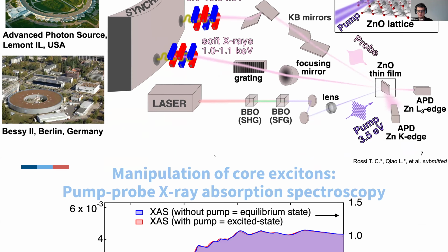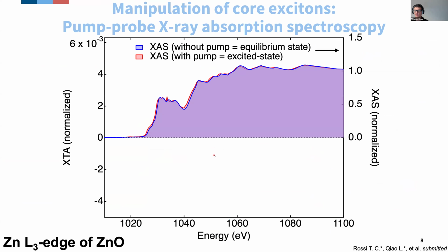And so with this, I will finish my introduction by just showing how experimental data are actually depicted. What we record are X-ray absorption spectra of semiconductors in two different sets of conditions. One is when the sample is not excited by the optical laser. This is the so-called equilibrium state, highlighted in blue. And we also record one spectrum when the sample is excited by the optical laser. That's the excited state, highlighted in red.